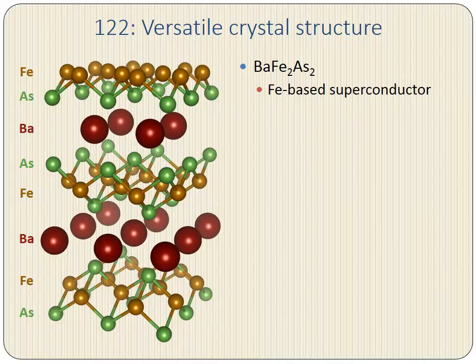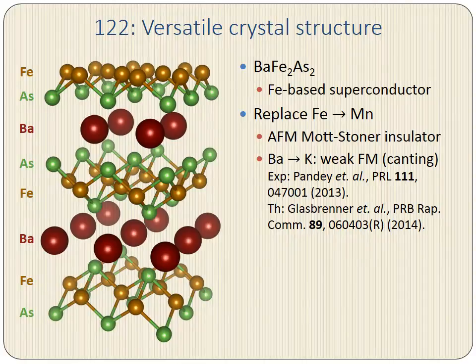The prototypical example is barium iron arsenic, which has a planar structure with iron planes that form a square two-dimensional lattice. We note that this structure stands up remarkably well to the substitution in and out of different ions. For example, if you replace all of the iron atoms with manganese, the same structure remains stable, and you get a new material, barium manganese arsenic. This material is an antiferromagnetic Mott-Stoner insulator. In addition, you can hole dope the material by replacing some of your barium atoms with potassium, and this will induce a weak ferromagnetism. That weak ferromagnetism was studied in the following experimental paper, and in the following theoretical paper in PRB Rapid Communications, we explained that this weak ferromagnetism is due to an on-site canting of the manganese moments.